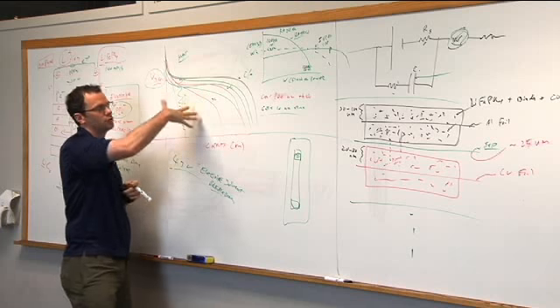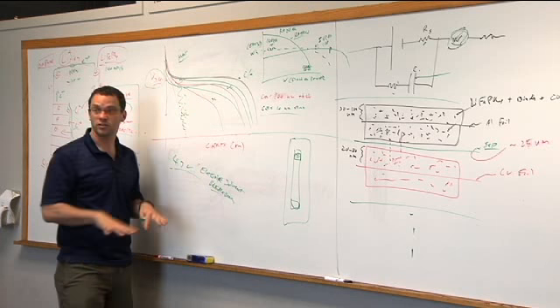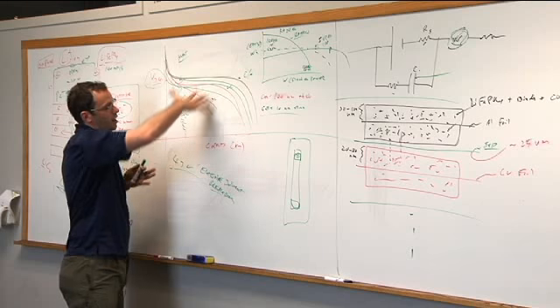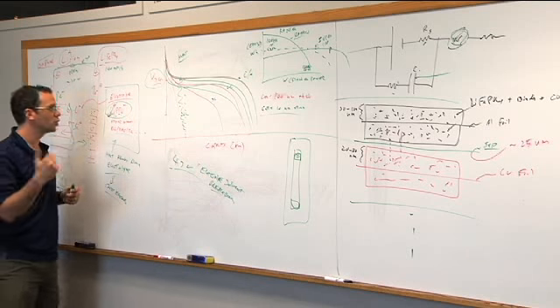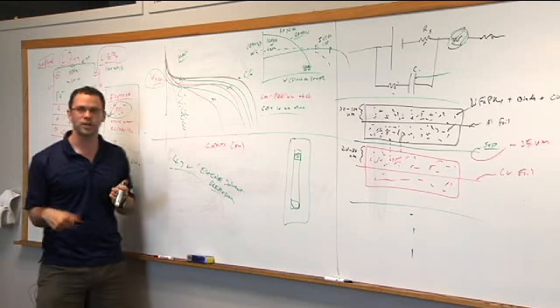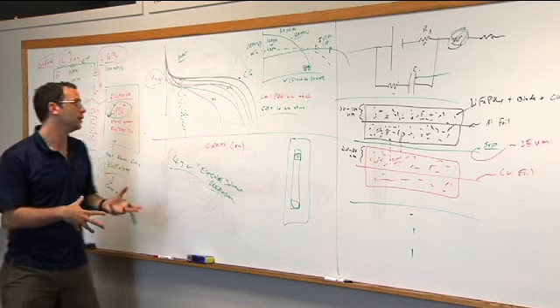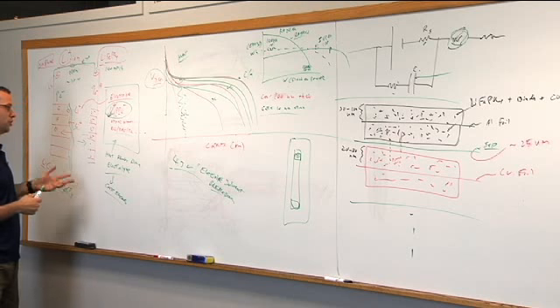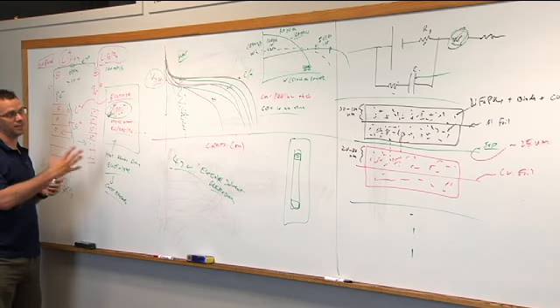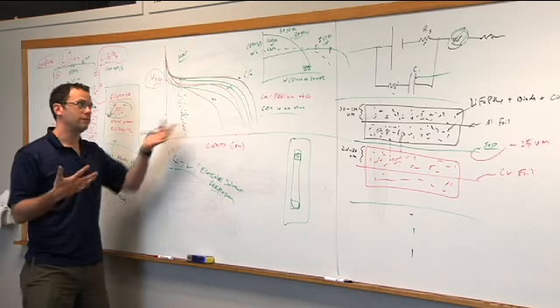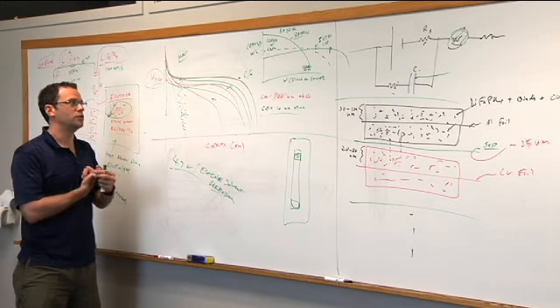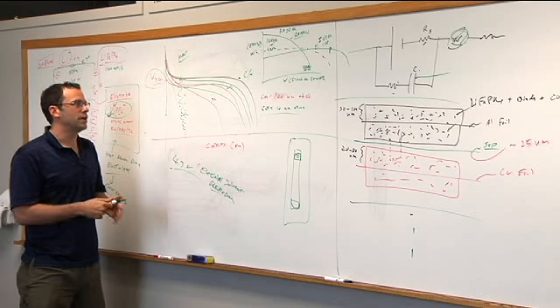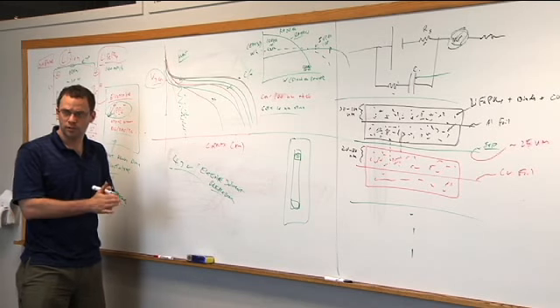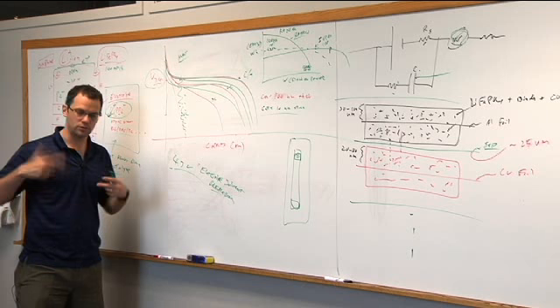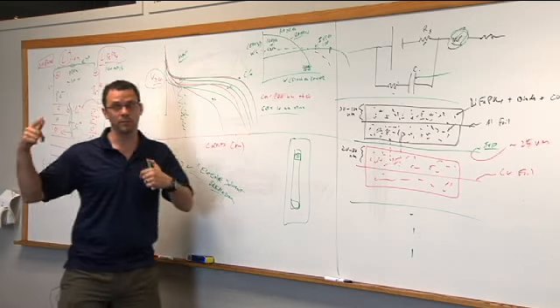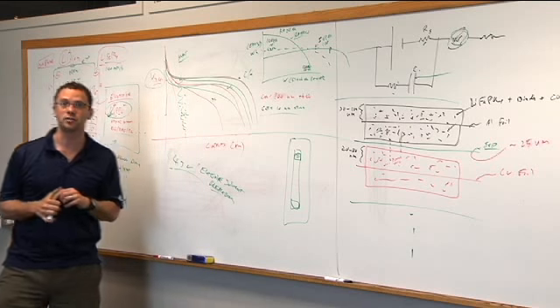And you're going to get some of this, right? Because at low temperatures, my diffusivity is going to be lower because it's a kinetically motivated process, and you're going to have more concentration polarization. You'll starve out a little bit earlier. But the good news is there's an argument for doing some pulsing at very low temperatures to heat up the inside of the battery. You're only going to heat it up a couple tens of degrees Celsius. You're still going to be well within your comfort zone because you're not going to be at 50 or 60 degrees C anytime soon. And in fact, you'll get better performance. So at very low temperatures, what you really want to do is perform a current ramp, where you start with 0 amps and ramp the current up at some rate to heat it up, let that happen for a couple minutes, and then you can start to use it more like you'd expect to be able to use it.